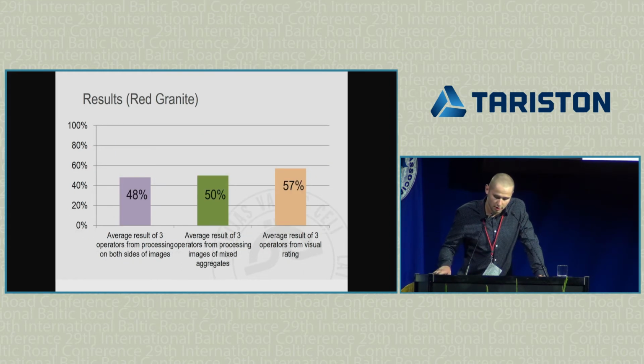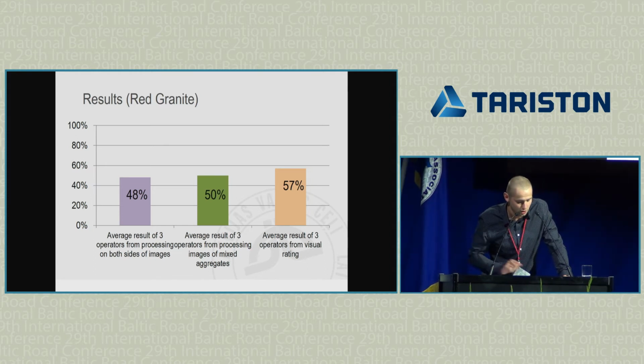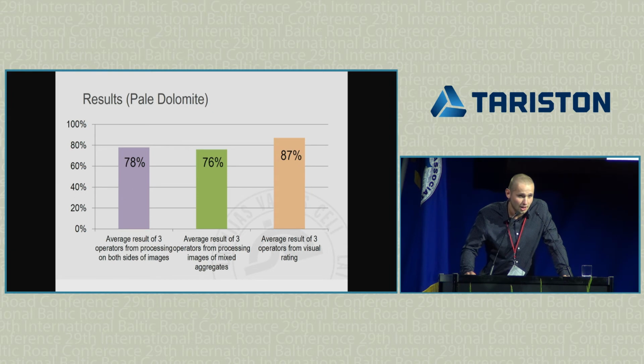For the red granite, the difference is bigger. It's about 7% between visual method and photo processing. The photo processing method shows us a lower bitumen coverage. And for the pale dolomite, the difference is the biggest. It's about 10%. And it's a significant difference.